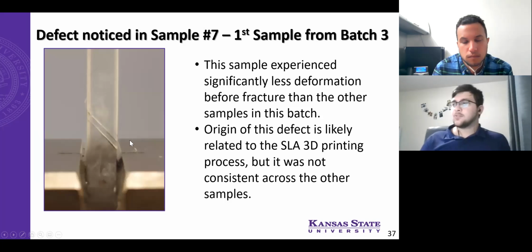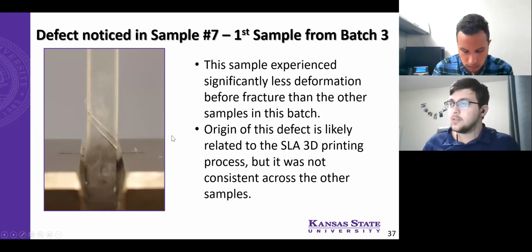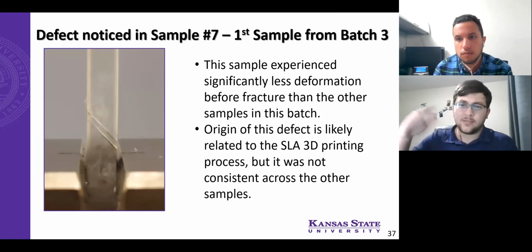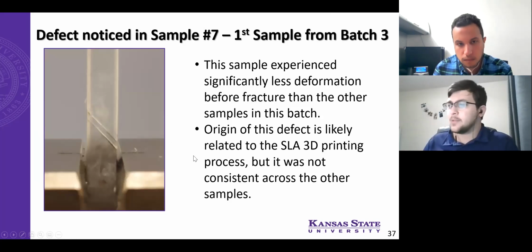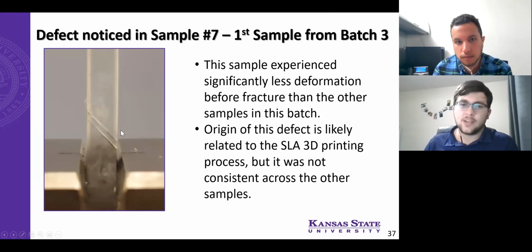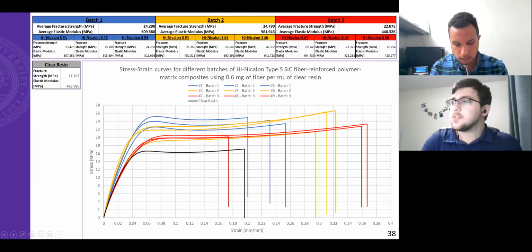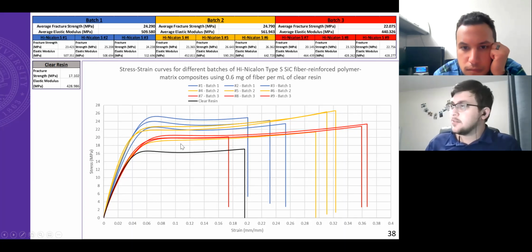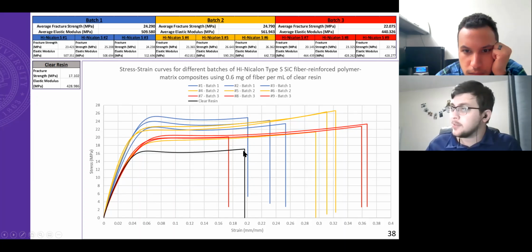My initial guess as to where this came from would be from the layer printing from the SLA printing, but it wasn't observed in the other samples, so I'm not entirely sure that could be the case. And then here is the comparison of all of those batches against one another. So not the most consistent in a sense, but consistently higher fracture strength when compared to the neat resin here.